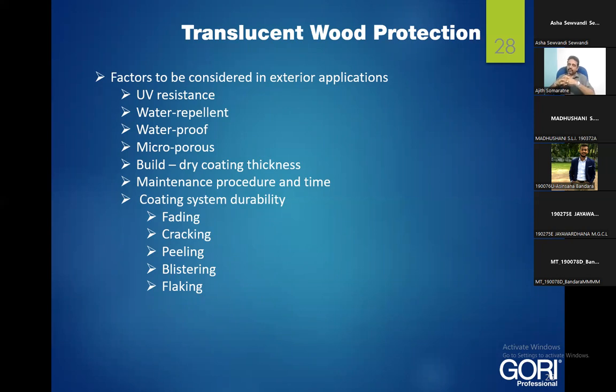Actually, it's like this. Wood is a porous material, right? After we dry it, the water or moisture will go away, but air will go into the wood and the pores will be filled by air. Now we coat it using a wood protection coating or a paint or something. We cover it. Then when the temperature goes high, the inside air starts to expand. Then a pressure develops, right? If the coating is well bonded to the wood, there's no space for air to go out. So when this happens repeatedly, the pressure needs to be released, then the wood will crack to release the pressure. Or otherwise, if there are some joints, then the joints will be displaced or expanded. Then from those areas where the coating is not applied, this pressure will get released.